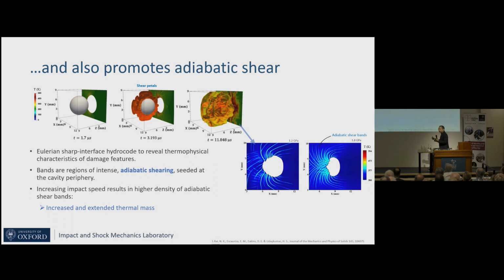And if it comes to thinking about how we might use it in terms of designing, we could then deliberately place cavities in a certain spatial distribution and exploit the fact that they will all give off heat at a certain time. Okay. This is a rather coarse model. It looks nice, but the details of how we actually controlled or allowed that material to fail within the numerical code is actually really coarse. And so we still don't have any real good information about, at those conditions, the very, very high strain rate conditions, the very high temperature conditions, how that damage and how that plasticity actually evolves.